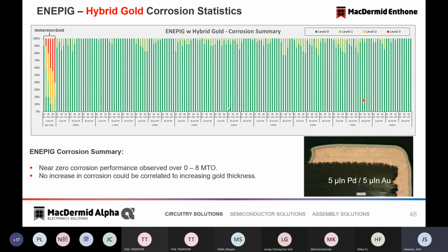Now, back to your original point, of voiding. I don't think of it as voiding, because when we have an electroless or immersion coating that is in the area of, let's say, 0.1 micron, 0.2 maximum micron, when you have 0.1, 0.15 micron, maybe 0.2, you really don't have a fully continuous surface.